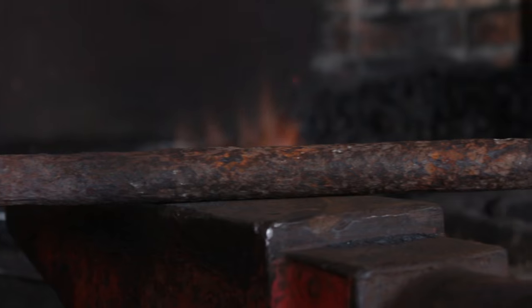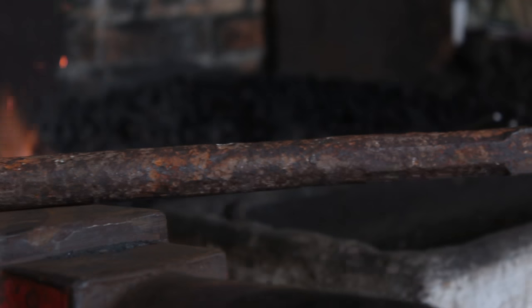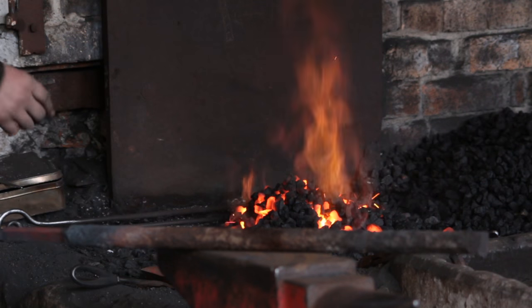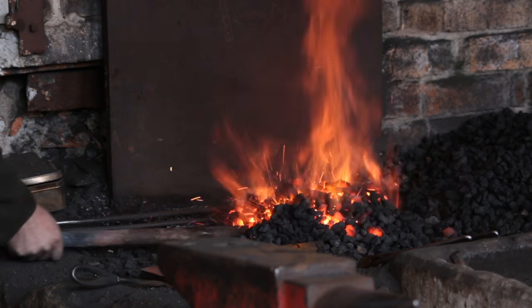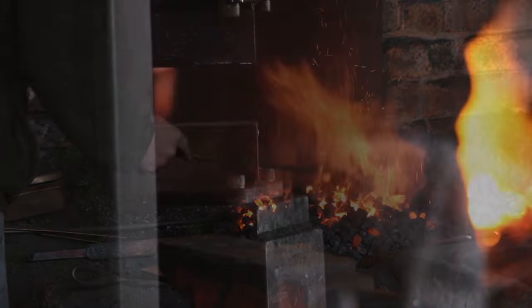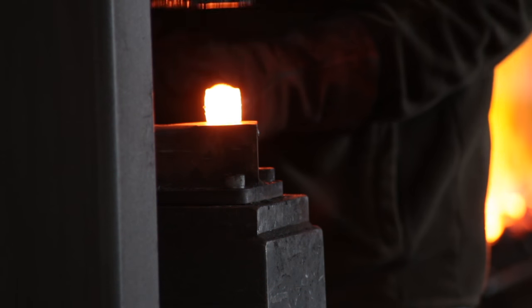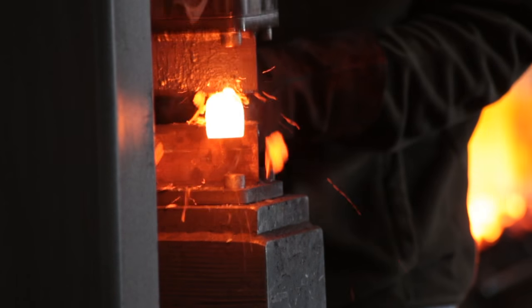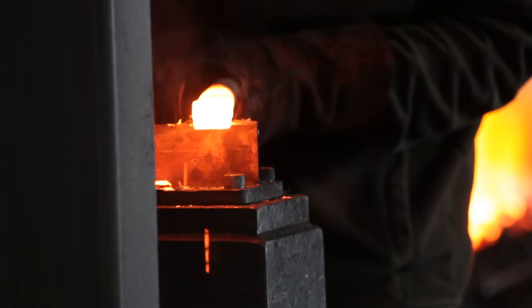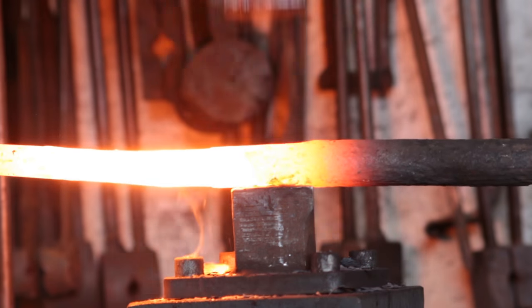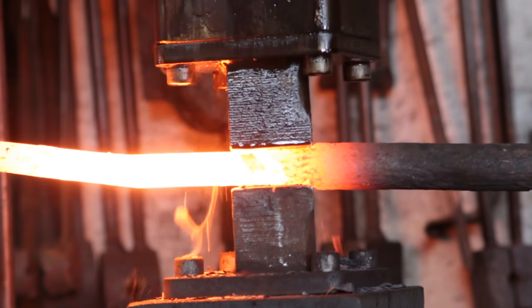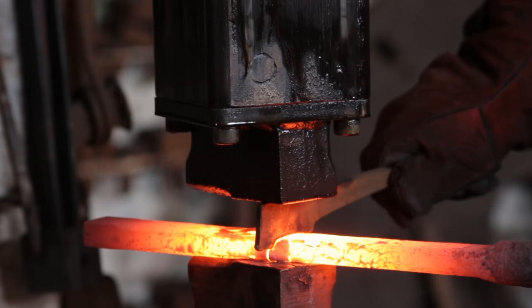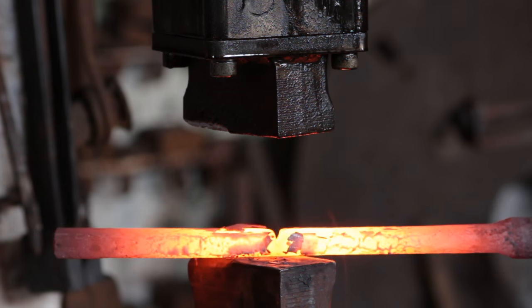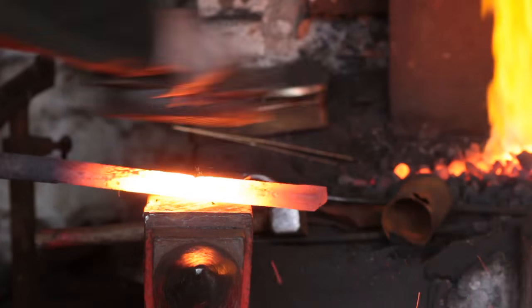The iron's quite coarse. So what I'm going to do is draw it out and weld it over a couple of times to try and refine the grain a bit. Wrought iron's quite nice to work with if you work it properly. Because this stuff is quite coarse, it tends to need to be worked at a welding heat. In fact, even the finer stuff, it's good to work it at a welding heat. So draw it out flat and fold it over, and then I will weld it up again under the power hammer.